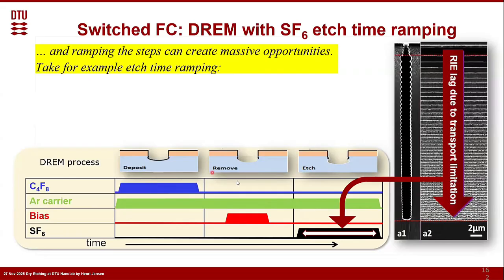While we have done this perfectly matching deposition and removal step, the etch step is free to be whatever. And we can now use what we call ramping. During every cycle, this time can be slowly increased. And we saw before that RIE lag is causing that while you go down, due to this Knudsen transport limitation, it's getting slower and slower. So less and less radicals are etching here. Although the time has been the same for the whole cycle, when you go to high aspect ratio structures, it cannot etch that deep. Not all the radicals are reaching the bottom.